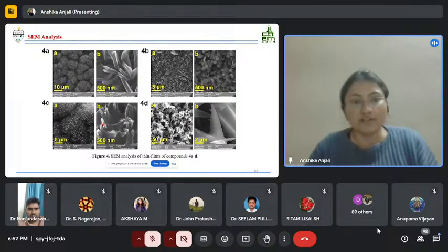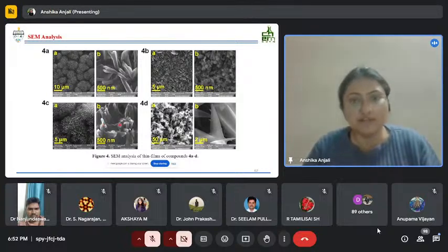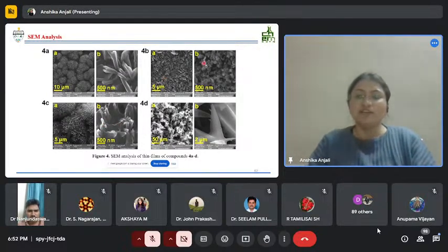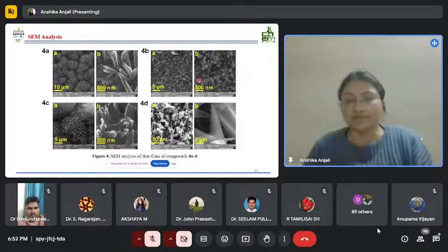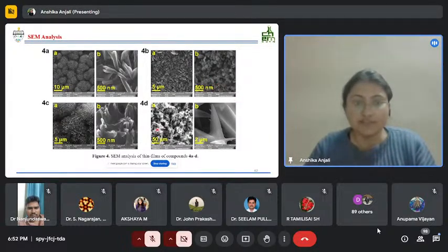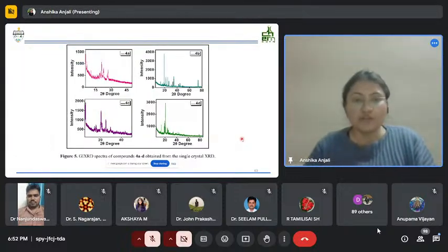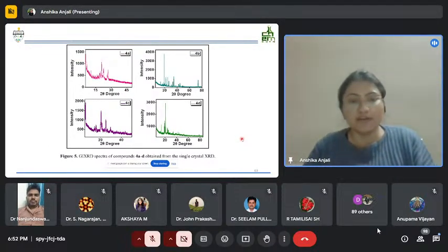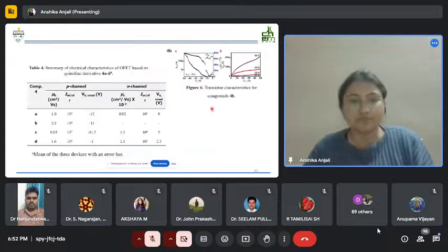Here the first compound, 4A, resulted in flower-like morphology. For compound 4B with the 4-methoxy substituent, although the packing is dense, the morphology is a bit different. Compound 4C, with the tertiary butyl group, resulted in flower-like morphology, and this is the morphology of the biphenyl substituted compound. Their GIXD spectra were recorded, and sharp peaks for compounds 4B, 4C, and 4D support their polycrystalline nature.